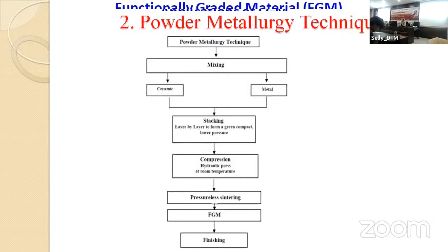Another method, I'm sure you know, is the powder metallurgy technique. In the powder metallurgy technique, we are mixing, for example, a ceramic and metal, and we are stacking layer by layer from the lower pressure, and at room temperature we use compression by a hydraulic press, and after that we just sinter using thermal energy, not pressure. Pressureless sintering, and then we get FGM. It's a method.